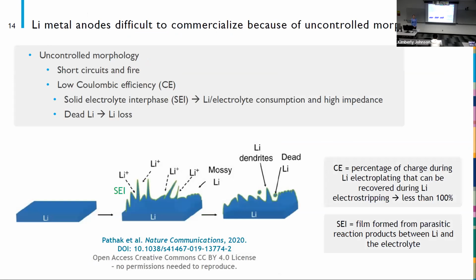So why hasn't this worked, and why aren't lithium metal batteries in your cell phone today? Well, lithium metal electroplates in an uncontrolled morphology. We'd like it to plate like that on the left, where it's just a nice dense block of lithium, but it doesn't actually do that. Instead, it forms these high aspect ratio structures that look like dendrites. That's what we tend to call them, or mossy structures. And those mossy structures and dendritic structures can actually short circuit the battery by growing through the separator and cause fires and safety problems, as well as performance problems.